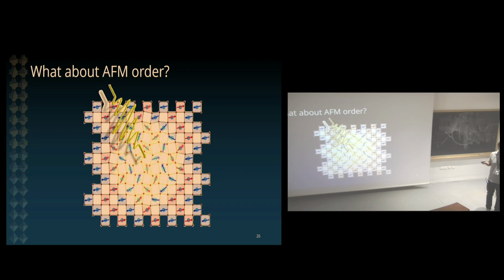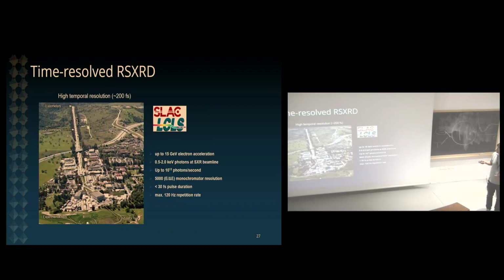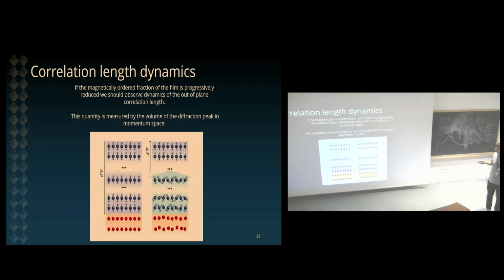So what about the antiferromagnetic order? What's going on there? In order to probe antiferromagnetism, we had to go all the way to the United States, to the LCLS. That's a facility that allows you to probe your system with pulses of X-rays that, at the time, could be of the order of 200 femtoseconds. Now the new generation light sources are aiming for femtosecond pulse lengths. So that's a future development. In the future, we could even probe this type of dynamics with much more detailed temporal resolution. This experiment was done about 10 years ago with 200 femtosecond resolution.